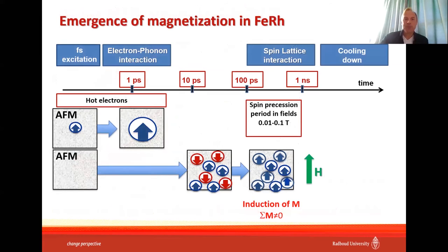And actually we can now build up the whole picture of what's going on, and resolve all the controversies that were in the field up to now when we talk about the physics of phase transition in iron rhodium. Here we have femtosecond excitation, electron-phonon interaction, lattice interaction and cooling down. This is the time scale: 1 picosecond, 10 picoseconds, 100 picoseconds, 1 nanosecond. So with femtosecond laser excitation, we induce hot electrons, and as a result we pump a lot of energy into the system.